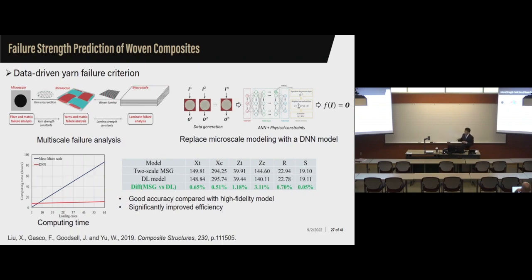And if you compare the efficiency, it depends on how many Gaussian points you have and how you are going to use the failure criterion for the yarn. Of course, if you don't use it much, because you need to generate significant data for the training purpose, the initial cost of the deep learning model will be high, about 8 hours. But if you use the failure criterion, numerically machine learning the failure criterion more and more, then you'll find that compared to the physics-based multiscale simulation, the machine learning model cost will remain the same. Because once you learn, then it's a polynomial, okay? It's a failure criterion for the yarn, and then you can use it again and again.